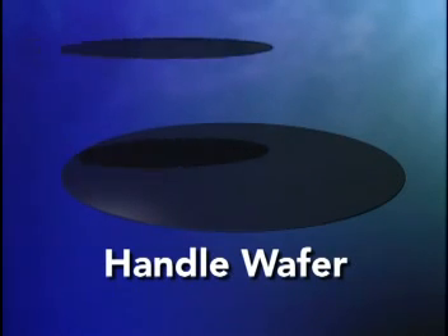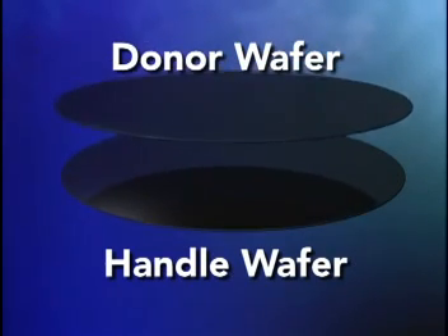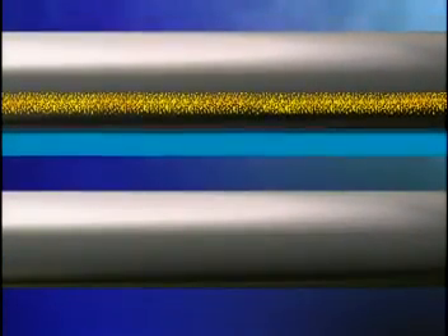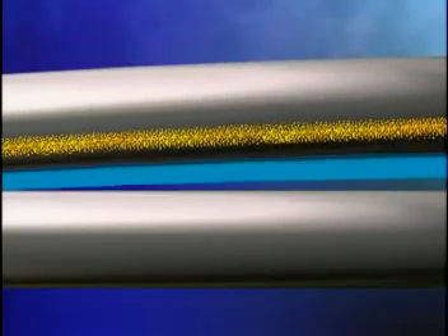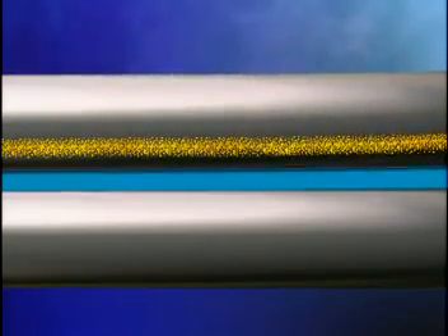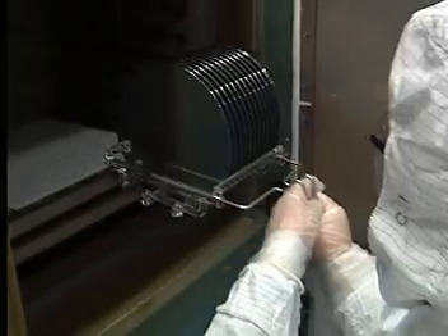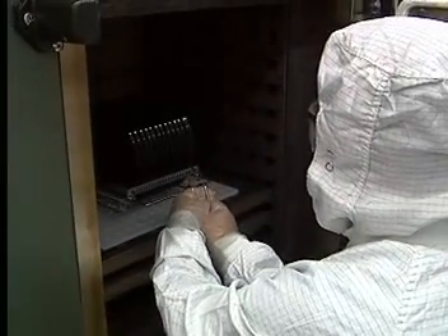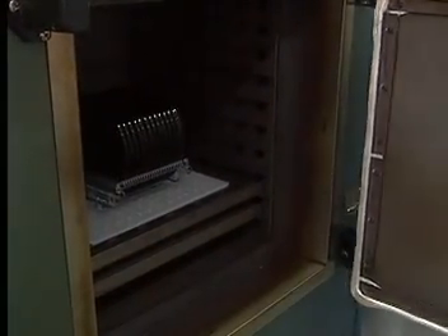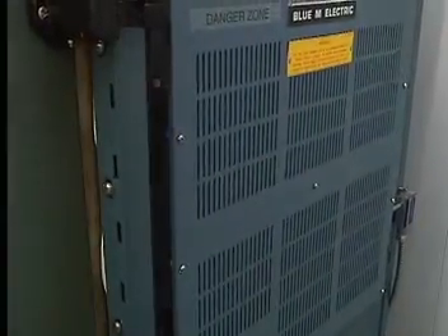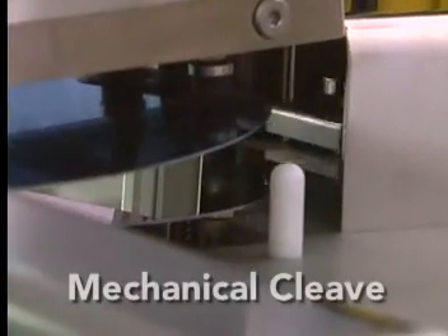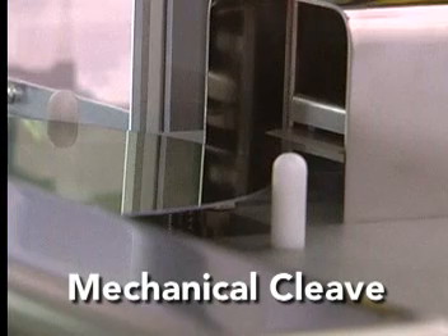The donor and handle wafer surfaces are brought into contact and a gentle compressive force is applied at one edge of the wafer pair. This initiates a bond wave that travels across the entire bond interface area, bonding both wafers together. The bonded pair is given a treatment to further increase the bond strength. The bonded pair is now ready for the mechanical cleaving process.